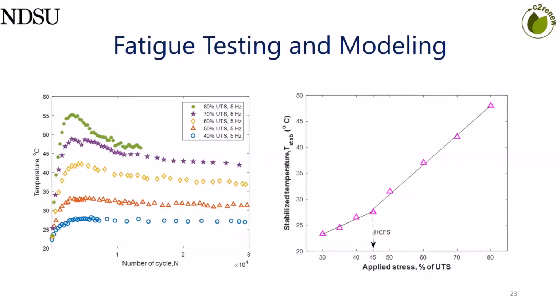Another aspect we've looked at as a group is the durability, the long-term performance of these composites. We've used different fatigue testing and modeling approaches to determine things like high cycle fatigue strength of these different types of composites. We can do so by testing at different temperatures and at different frequencies, and we've published quite a bit of work on that long-term behavior.